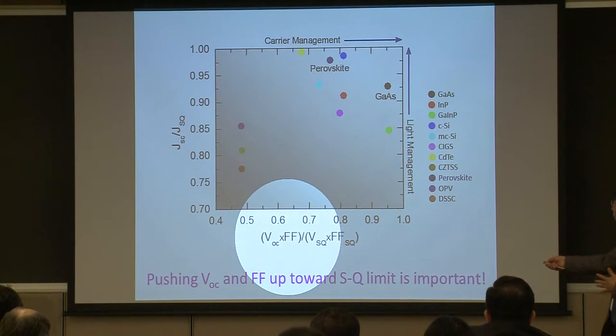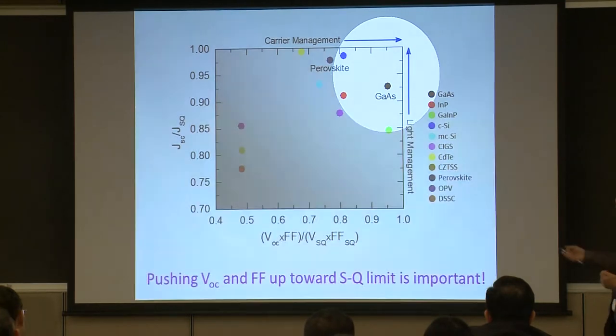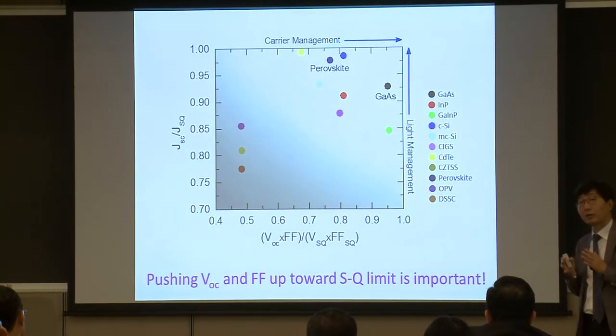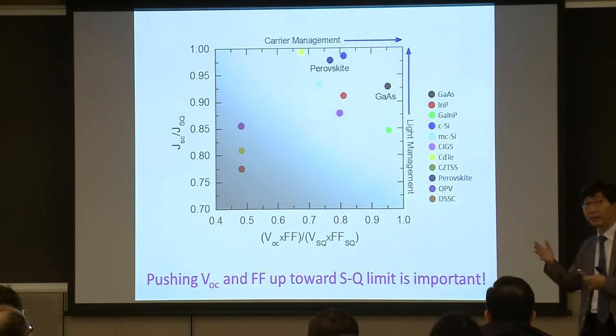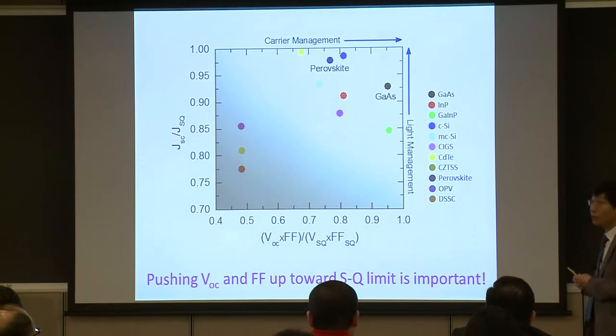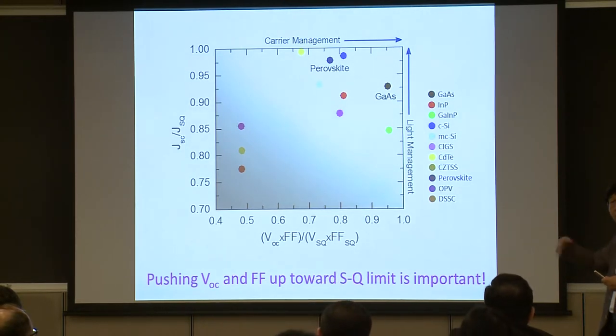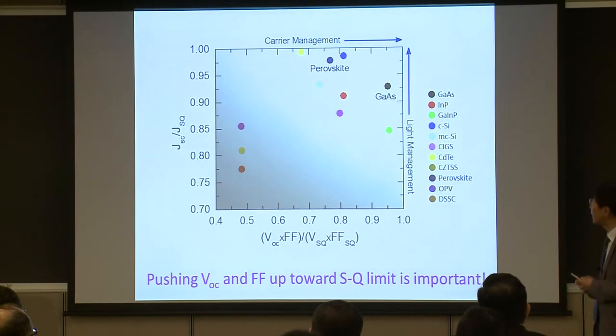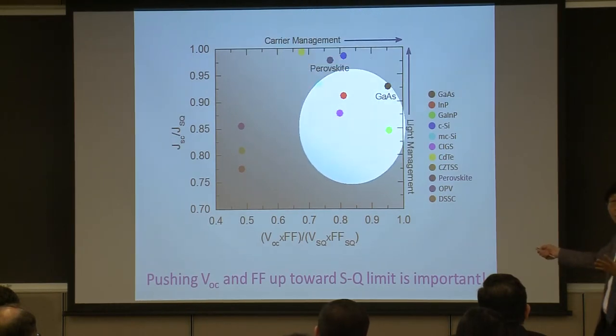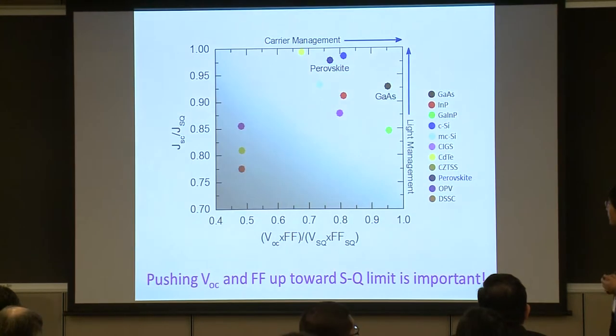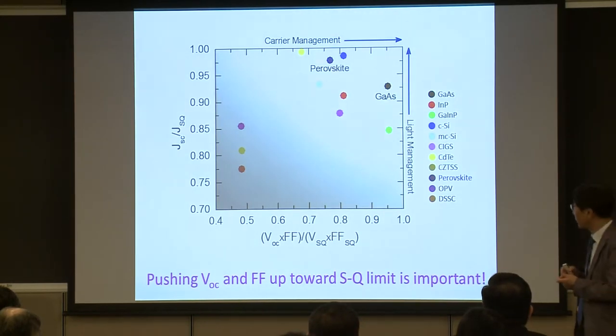So for the case of gallium arsenide, they already achieved the very good open circuit voltage and fill factor here, but slightly lower short circuit photocurrent density. So for gallium arsenide, people try to increase the short circuit photocurrent density, which is a strategy for improving further the gallium arsenide solar cell. But for perovskite, we already have pretty good photocurrent density, but pretty low open circuit voltage and fill factor. So we have to focus on increasing open circuit voltage and fill factor.